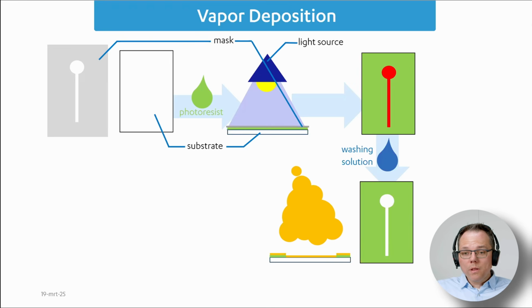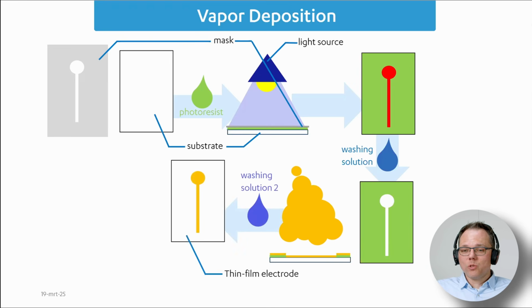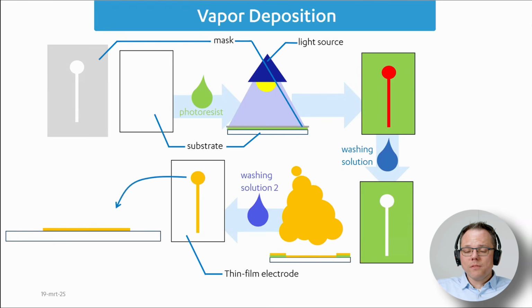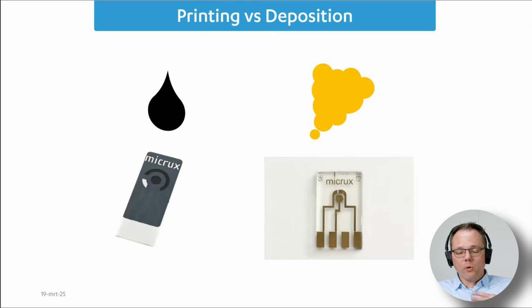It deposits on all the parts, but then we wash away the remaining photoresist with a different washing solution, and only where, in this case, our gold has been deposited directly on the substrate, it sticks to the places where we want it to be. The result of that is a very thin film, around 150, 200 nanometers, and this is pure metal. So this is a very different type of electrode. And these are two very well-known ways of doing it.